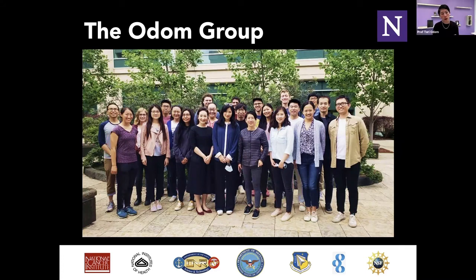of the hotspots? Okay, so let me just be clear about how we get the SLR. As I mentioned, it's the localized surface plasmon of the individual particle coupled to the lattice. So we cannot just arbitrarily change the localized surface plasmon properties to get that good SLR. For example, say you have 100 nanometer particles on 400 nanometer spacing, and you have the perfect SLR, something with a Q factor of say 500. If you change the particle's size, even though you keep the lattice the same, you're going to detune the SLR, because the wavelength of that localized surface plasmon is no longer at the optimized wavelength to couple to the diffraction mode to get the SLR at the wavelength that's mostly governed by the periodicity. So there are some trade-offs there.